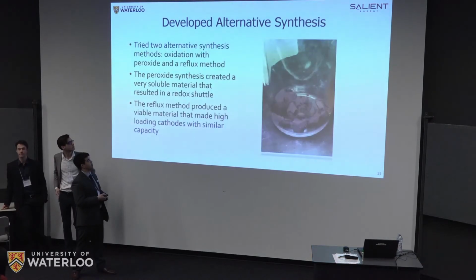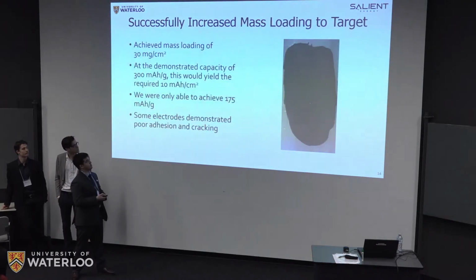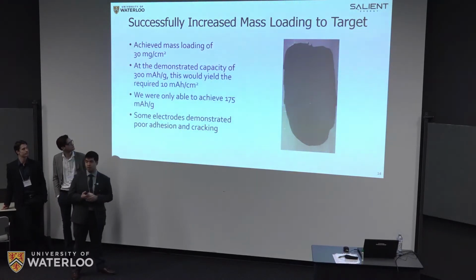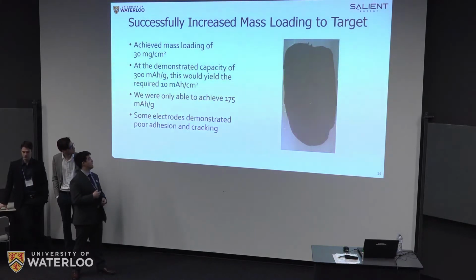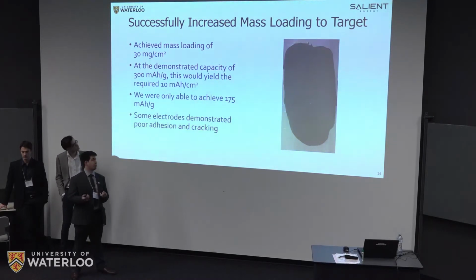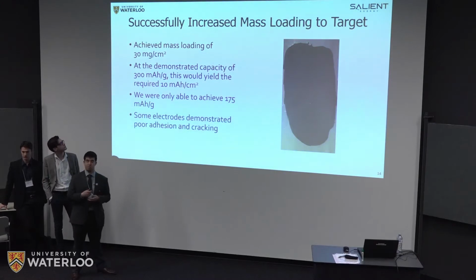One of the first things that our group was able to do was increase mass loading to our target of 30 milligrams per centimeter squared. Based off of the Nature paper, if we were to have the demonstrated capacity of 300 milliamp hours per gram, we would have the 10 milliamp hours per centimeter squared for areal capacity that we needed. However, we were only able to demonstrate 175 milliamp hours per gram. Some of the cathodes even had poor adhesion to the nickel foil and also incurred cracking.